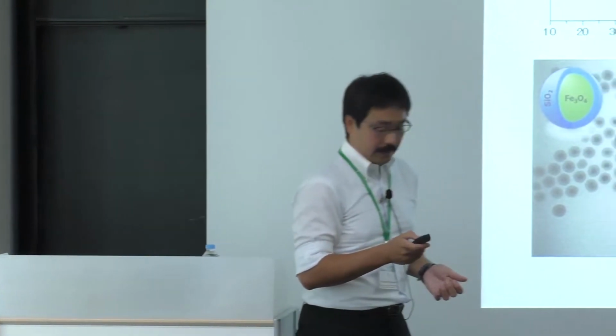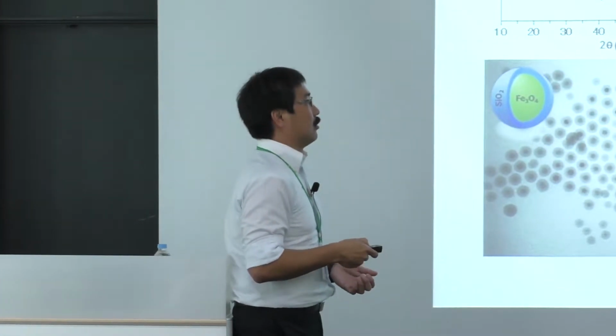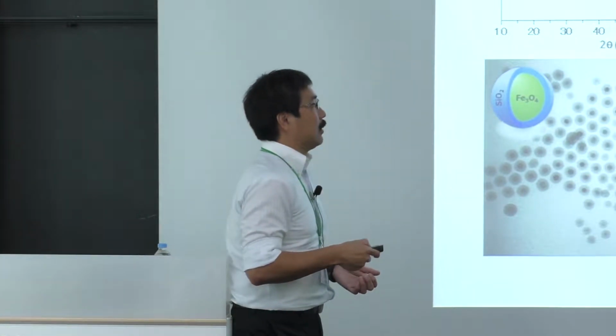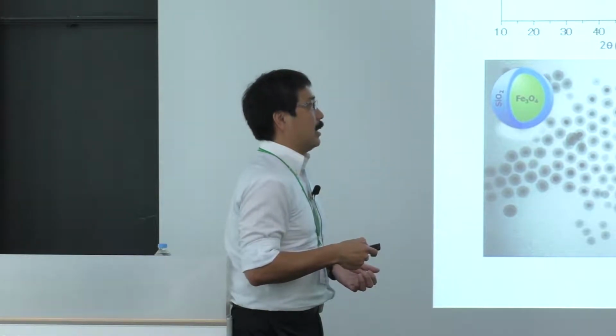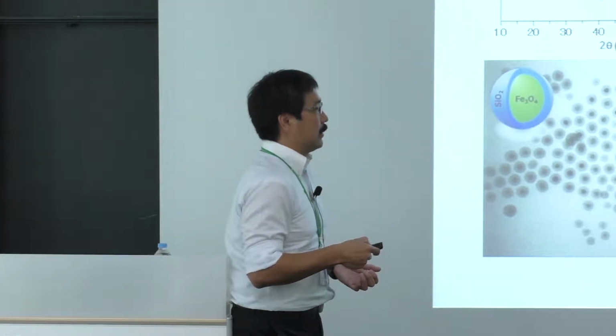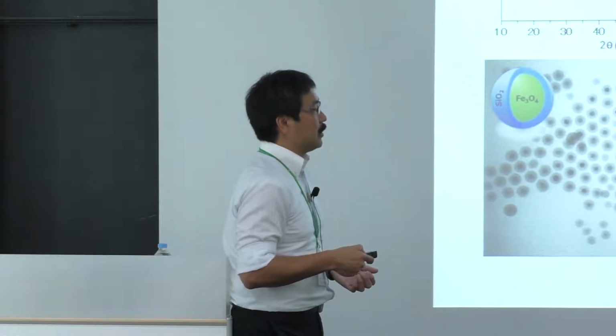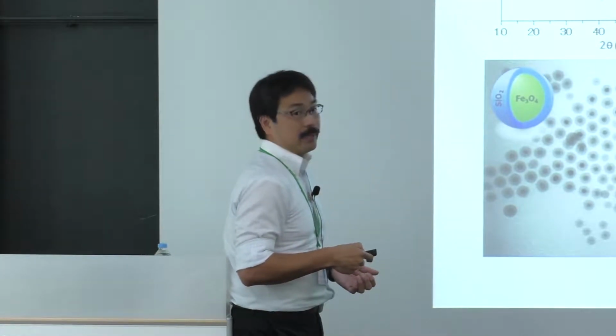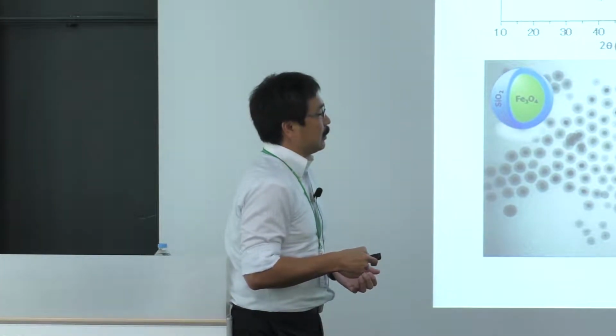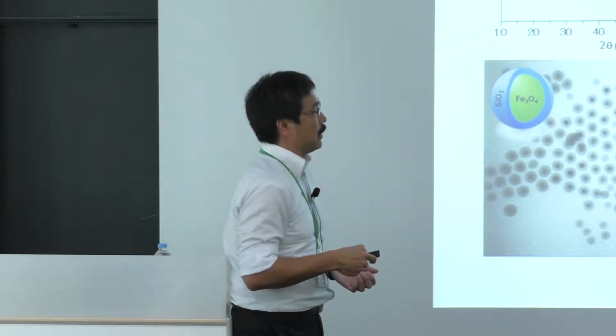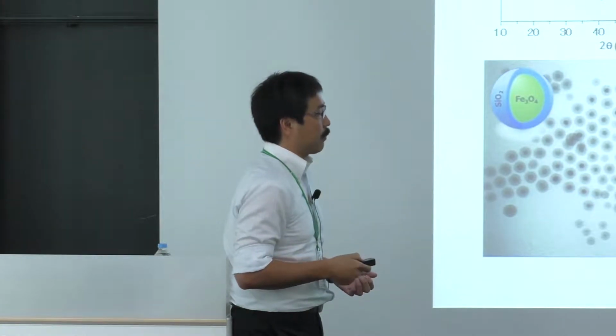In this slide you may find an interesting feature of this method. As this close-up view shows, our nanoparticles consist of an Fe3O4 core and a SiO2 shell, but we have voids inside the SiO2 shell. This brightest area between the iron and SiO2 is the void.